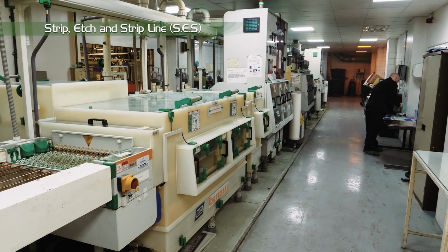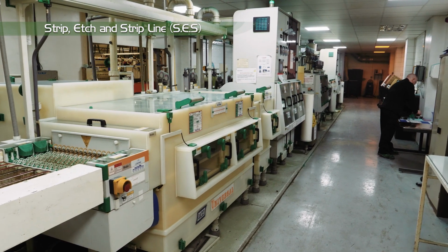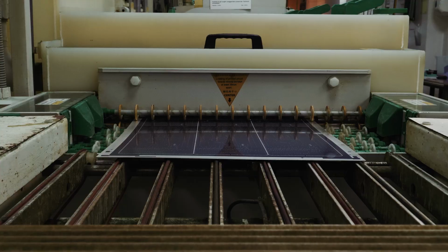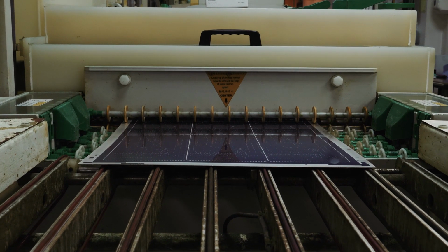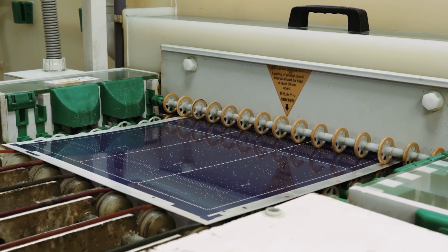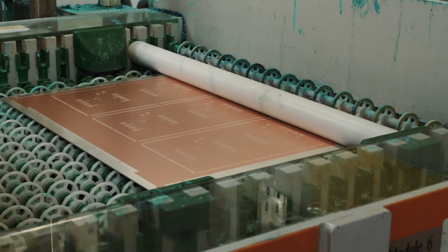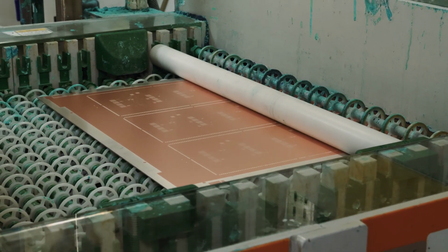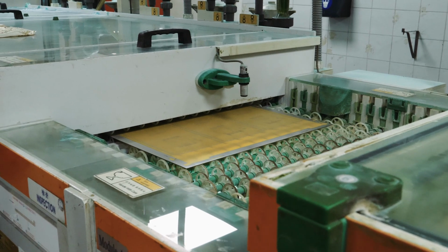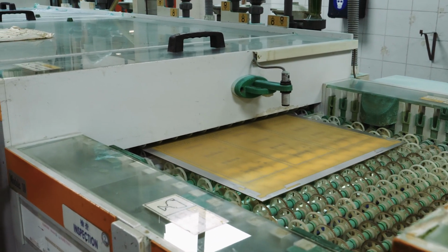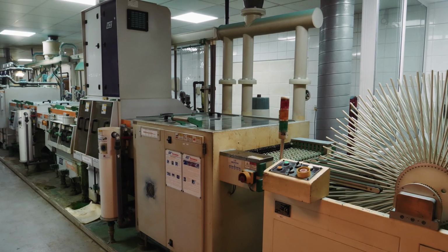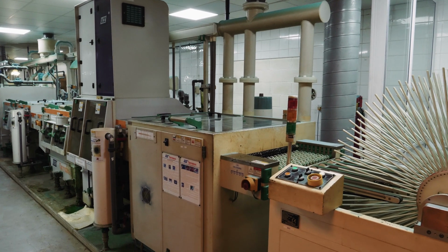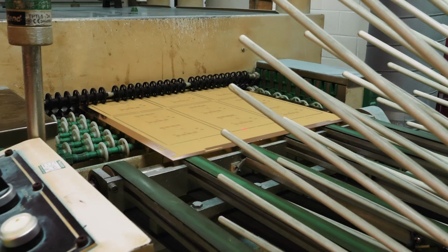The SES line, or strip etch strip line, firstly removes the plating resist, exposed and developed in the same way as the inner layer resist, then chemically removes the copper that was covered by the plating resist. Finally, the tin is removed, which was protecting the copper image on the surface and in the via. This leaves the circuitry that is required and the copper in the via that is connecting all the inner layers